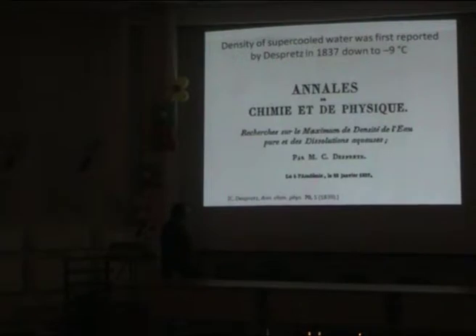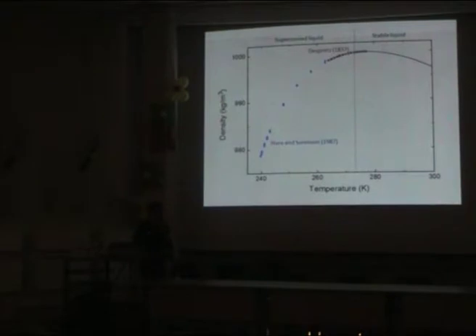please. The density of supercooled water was first reported a long time ago, almost 200 years ago. Next slide, please. And this property indeed shows that water is anomalous. At 4 degrees Celsius, the density of water exhibits a maximum, and upon further cooling, especially into the metastable region, the density goes down, unlike ordinary substances. 200 years ago, 100 years ago, of course, the supercooling was not significant, but now we have a dramatic decrease of density, which shows that maybe the derivative of the density with respect to temperature could even be negative infinite.